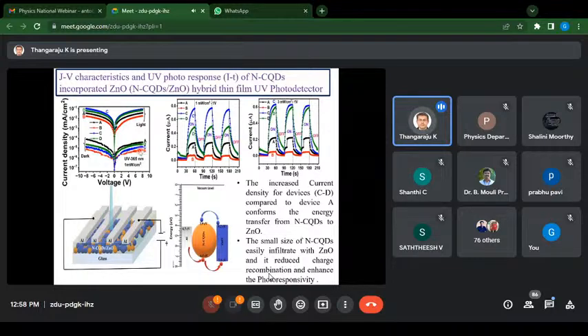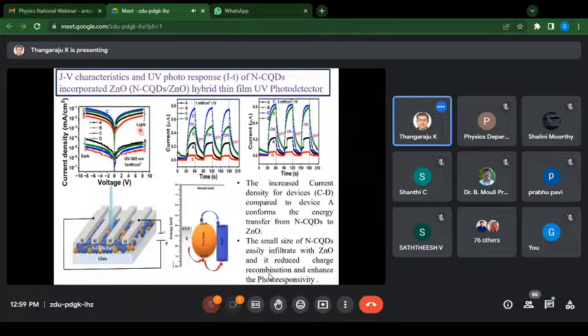So with the improved quality of the zinc oxide by forming the nanoparticles, the dark current is reduced, and also the absorption of the carbon quantum dots onto the surface makes the surface barrier larger than the pristine one, and hence the dark current is reduced. And when the UV light falls on this device structure, you can see that the light current is quite improved, which gives the higher device efficiency.